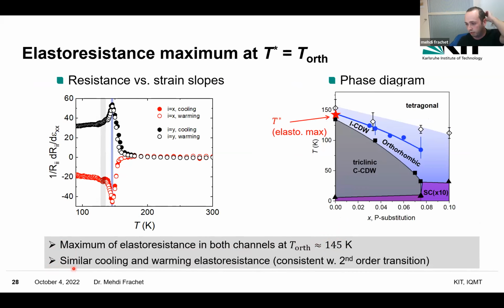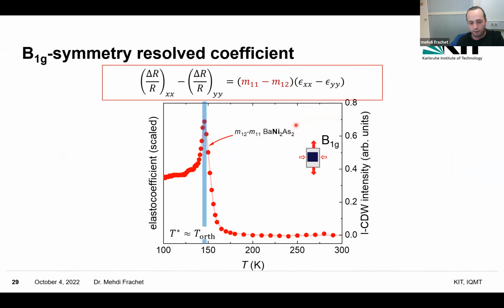And we have similar cooling and warming elastoresistance, which is consistent with a second order phase transition. So we can start to complete our phase diagram with this T star temperature of the maximum of the elastoresistance. So I've just put the first point.